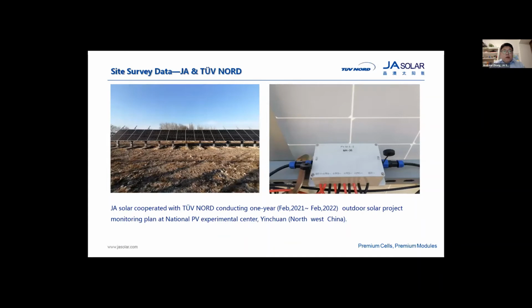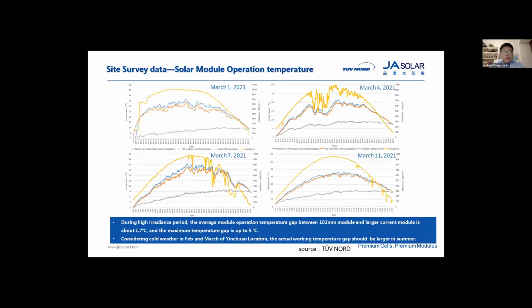For verifying the actual data, JA also cooperated with TUV Nord, conducting a 1 year outdoor solar project monitoring plan, which I think so far is around 3 months, at the National PV Experimental Center in Yinchuan, northwest China. During the high irradiance period, the average module operation temperature gap between the 182 millimeters module and the larger current module is about 1.7 centigrade. And the maximum temperature gap is up to 5 centigrade.